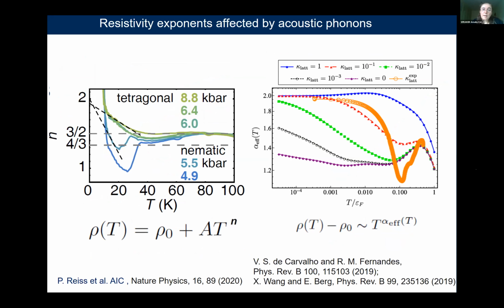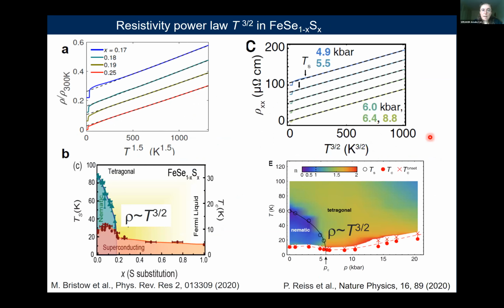And this type of coupling also has significant effect on the transport properties. And here I represent how the N coefficient varies with temperature. And these are with the studies under pressure, which we see that an exponent of about 3/2 is maintained for quite a large range at high temperature. But there is a variation in the exponent, and this type of variation in the resistivity exponent has been suggested to be a signature of the interaction of the system with acoustic phonons, so interaction with the lattice. And here again, I show you that at the nematic endpoint, we do not have linear T resistivity, but indeed, both with chemical pressure and applied pressure over a very large temperature range, we recover a dependence which looks like 1.5 or 3/2 dependence in the vicinity of the nematic endpoint.